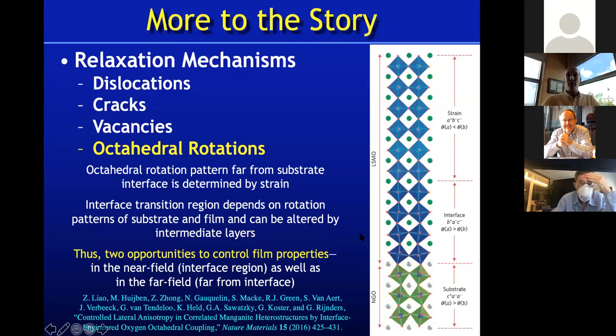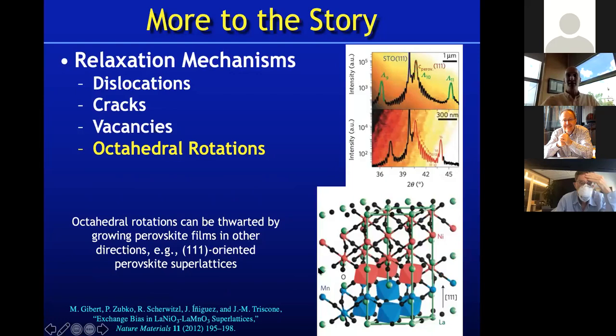Now, what our moderator has discovered is that by changing the connection at the interface, instead of being through a single point of the octahedron, by making it a 1-1-1 oriented octahedron, now there are 3 oxygens that connect together, which drastically frustrates the rotation of that octahedra. So there are all sorts of opportunities to do octahedral rotations as well as to thwart them. I should point out that in this case, as you go from 100 to 111, other complications can emerge. So in most perovskites, the low energy surface, so for a nice smooth film, is the 100 surface.